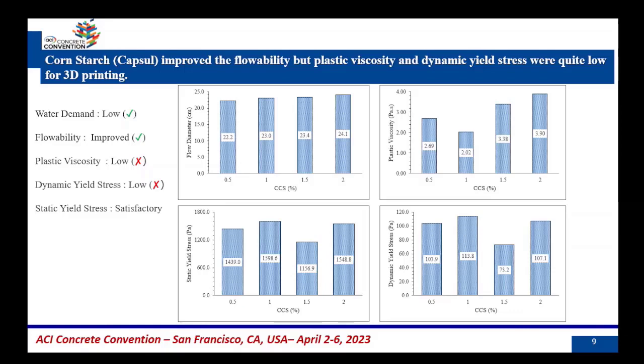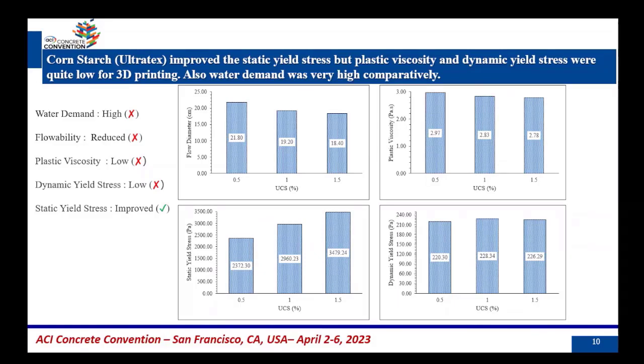So with the cornstarch of the Capsul brand, the water demand was quite low and flowability was significantly improved with adding this. But the main rheological requirements, that is plastic viscosity and dynamic yield stress, were quite low, so it doesn't satisfy the requirement to be 3D printable. Similarly, with the second cornstarch, in this case water demand was quite higher and flowability was reduced, and we experienced the same problem with plastic viscosity and dynamic yield stress, but static yield stress was improved significantly in this